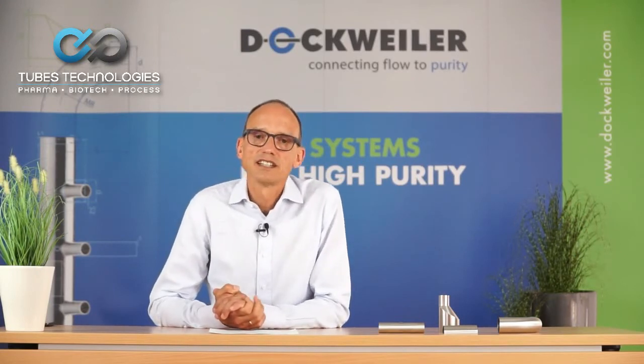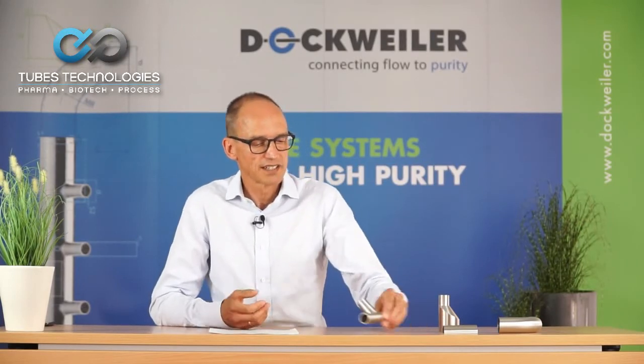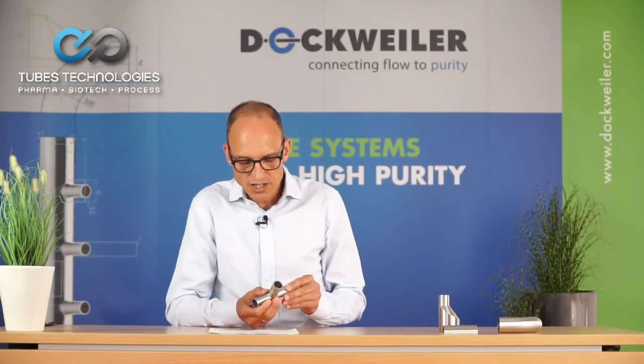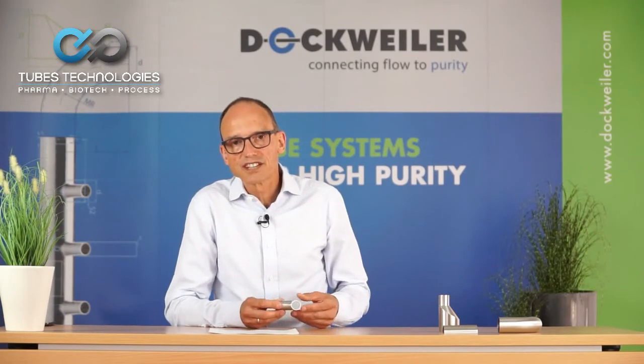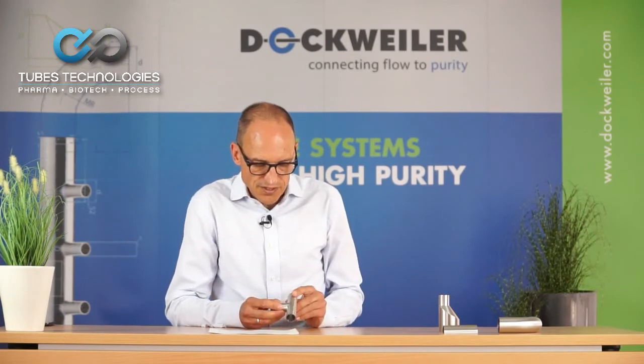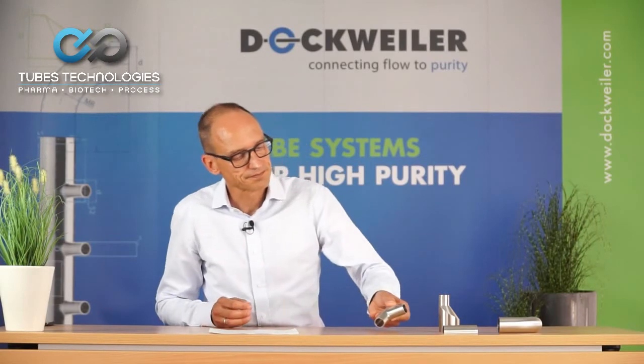And the second new topic here is that there are two options for the T-piece weld. Again, this is absolutely the same as with ASME BPE. The first one is that the T-piece weld is to be polished flush and smooth with the base metal on the ID and the OD, still maintaining the minimum of 75% of the nominal wall in all areas.